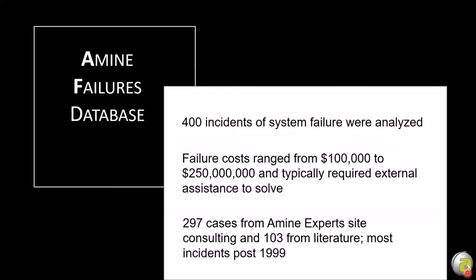So we have a database where we took the data from 400 separate system failures, and we analyzed them completely. Of those 400, almost 300 were ours, and then we took another 100 from the literature. And they were basically papers where we knew the author, we did a review of the work that they did and agreed that it was a well-written paper, and that's why we included it. Most of them post 1999, so it would have happened in the last 20 years, say.